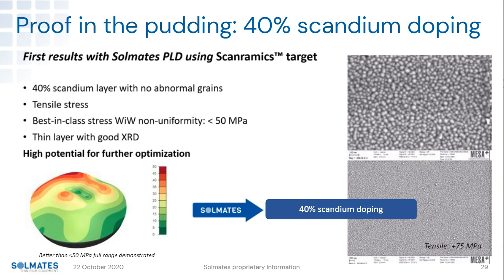So what we can do with 40% is vary stress, same way we did it for 30%. But the people that work with us will know that it becomes increasingly difficult to suppress, to avoid pyramids. So we managed to do it in a couple of weeks. We grow 40% scandium layer, pyramid-free. We can even do tensile.